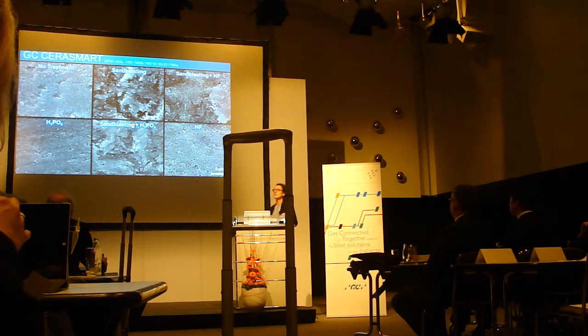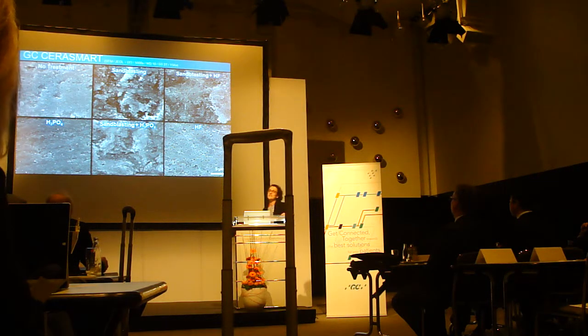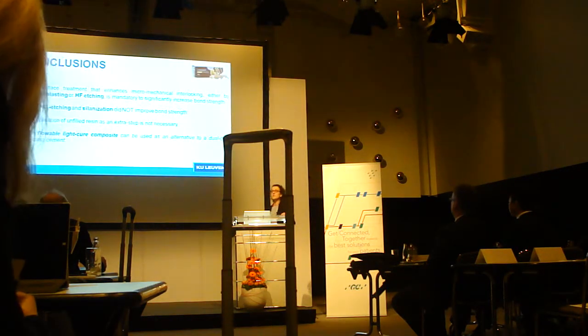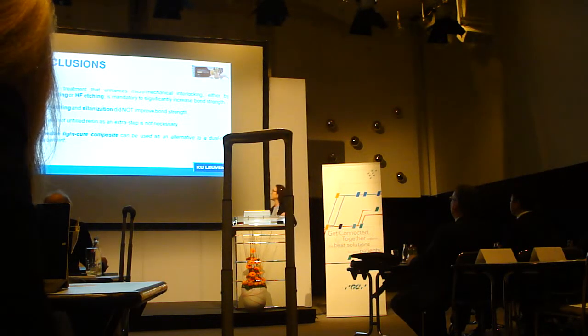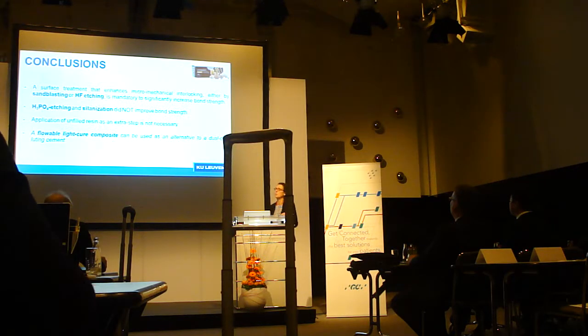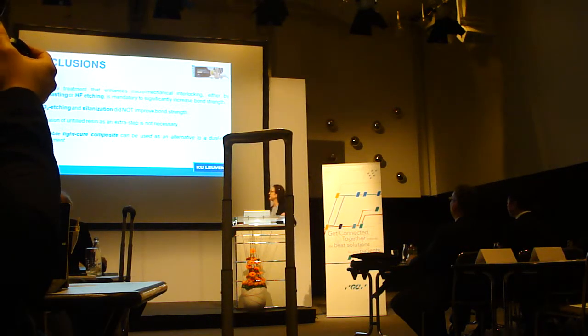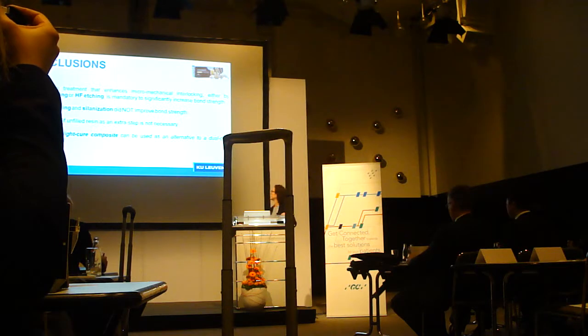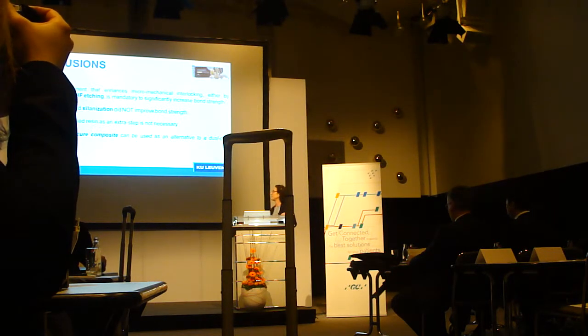Here we have the scanning electron microscopic pictures of the different surface treatments. They show that micromechanical interlocking is created by sandblasting and by hydrofluoric acid etching, and this seems to be quite important to have a good bond with the Cerasmart. Indeed, the conclusions of this in vitro study were that surface treatment that enhances micromechanical interlocking, either by sandblasting or hydrofluoric acid etching, is mandatory to significantly increase the bond strength. Phosphoric acid etching and silanization did not improve bond strength. Next, application of the unfilled resin as an extra step is not necessary. And finally, a flowable light cure composite can be used as an alternative to a dual cure luting cement.